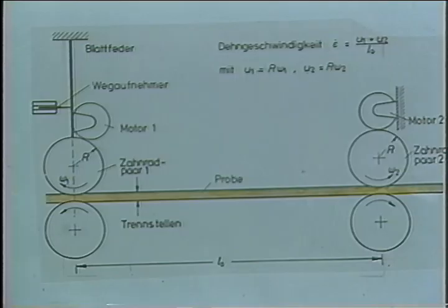The temperature has to be very uniform. Imagine you have a hot spot somewhere in the middle, then the sample would be stretching out in the middle, and everything could not be analyzed. The data could not be processed anymore. Polystyrene, for instance, has a much higher coefficient of temperature than polyethylene. So depending on what polymer you're using, you have to be more careful with the heating bath. So that's one reason why most data reported are on polyethylene and not on polystyrene.